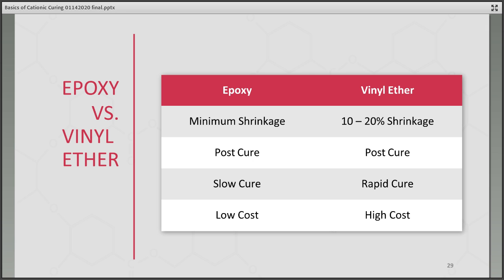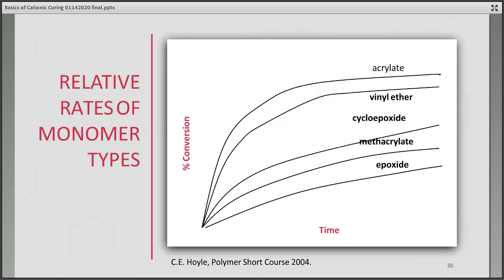So if you need to get your UV curable cationic formulation cured at a little bit higher line speed, you may want to add some vinyl ether. Again, a downside with vinyl ethers, because they're not available in as large quantities as the epoxy materials, they tend to have a higher cost. So in your formulation, you need to balance the pros and cons to decide, is it worth using.